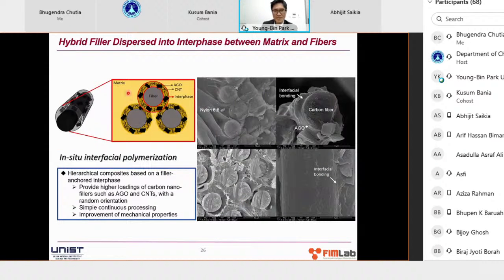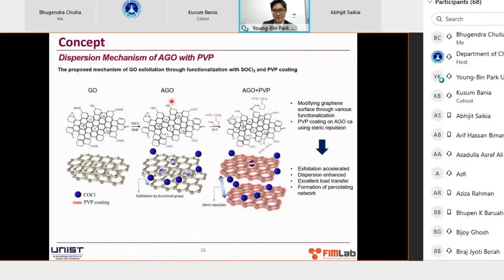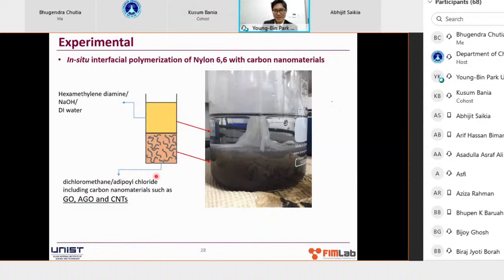So we have the carbon fiber here, the resin here, and between the resin and the fiber, we have the interface, which is like a thin layer, which contains the graphene oxide and carbon nanotubes. Please feel free to contact me later if you like these slides, because I need to skip through very quickly. Okay. So the key concept in interfacial polymerization is that on top you have an aqueous solution, which is composed of this here, and then in the lower half you have an organic solution, which is composed of these components and the graphene and carbon nanotubes mixed together.